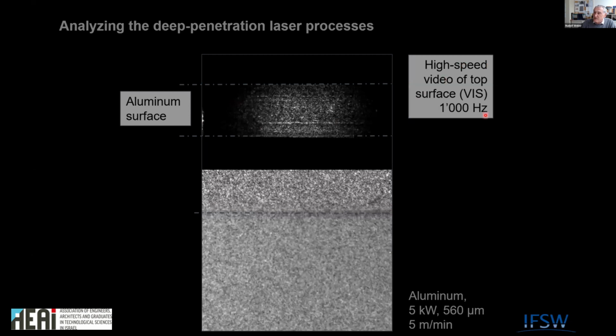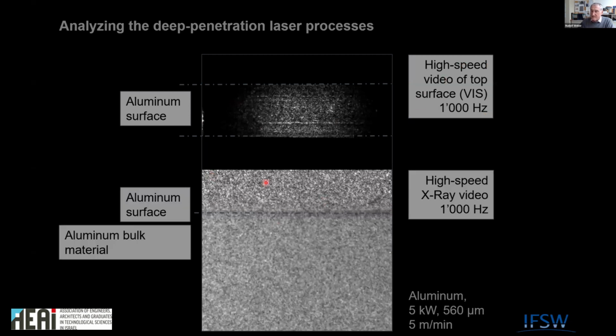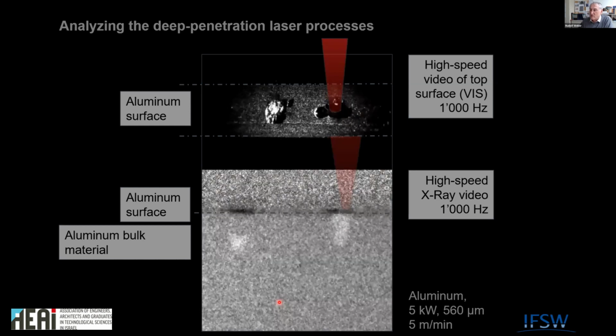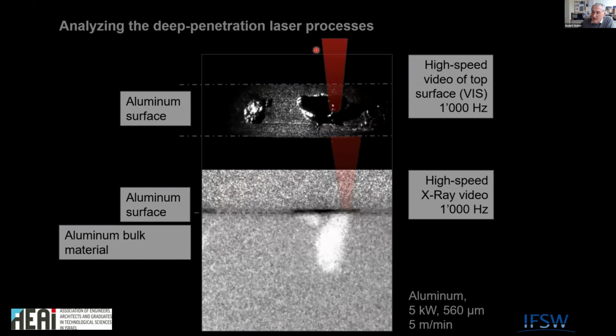Here we have a high-speed video with 1000 frames. And the lower part is, again, the aluminum part. Here is the upper surface. Here is a stop to prevent overexposure. And here is the bulk material. And what we see here is the X-ray video, now also with 1000 Hertz. And that's how it looks like. This is the laser beam coming. You see that on the top, you get an explosion. The process starts. We get a nice capillary.